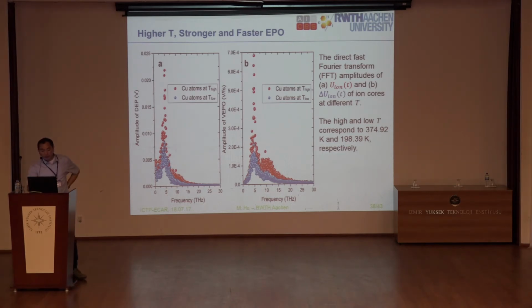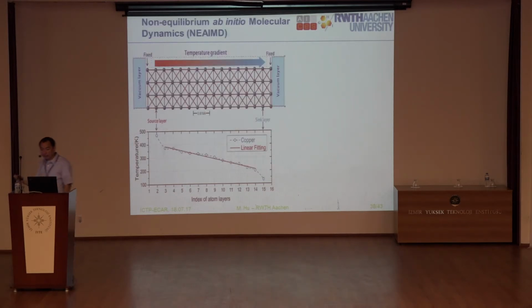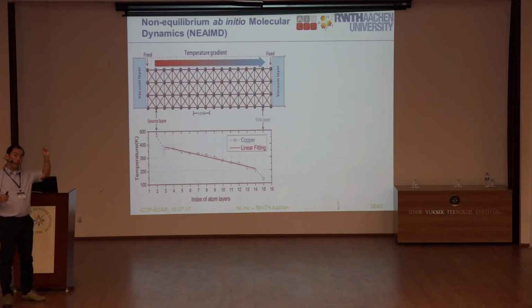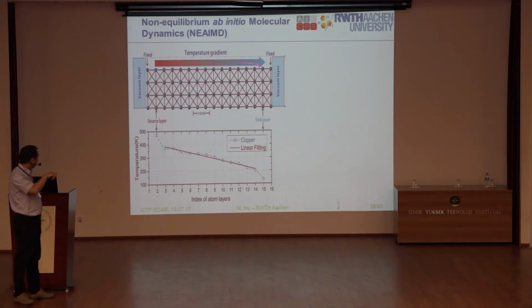And then we can find that, okay, with a higher temperature you have a faster electrostatic potential oscillation. So based on that, we can run direct non-equilibrium ab initio molecular dynamics. You can have a heat flux here from the heat source to the sink, and then the heat flux flows through, and you have the temperature gradient.